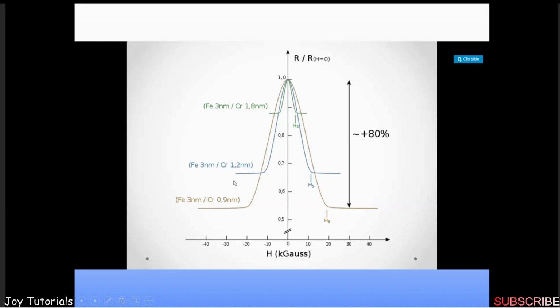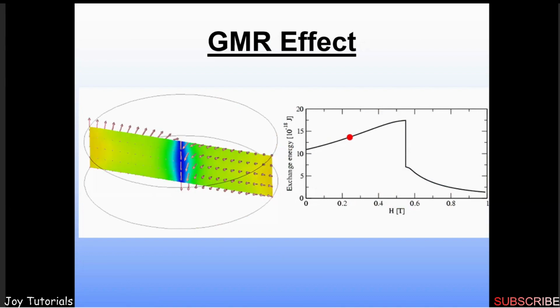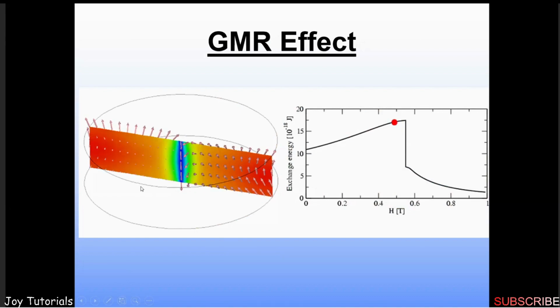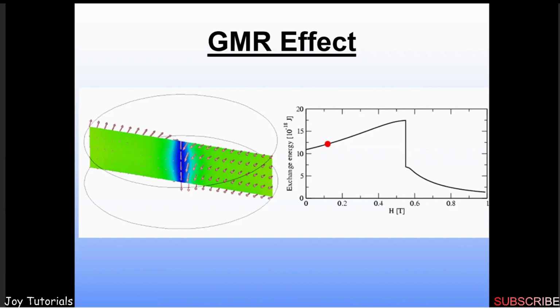If you increase the thickness of the spacer layer, the GMR value decreases. It decreases even more if you have a much thicker chromium layer. But the length scale is the important thing to see here. This is only possible for epitaxially grown single crystal thin films of tri-layers as well as multi-layers. Now, from here, how the GMR effect or the interface is changing, I think this is not the platform to go into the details of the theory, so I will skip this.